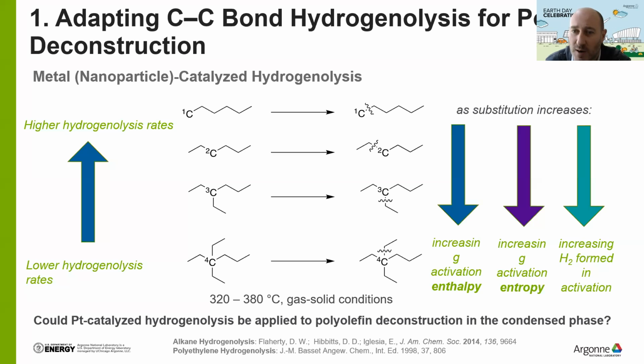The chemistry of carbon-carbon bond cleavage is well understood for small molecules. For example, there are metal nanoparticles that catalyze carbon-carbon bond hydrogenolysis, meaning using hydrogen to cleave carbon-carbon bonds. And this, as I mentioned before, is well understood in small molecules, C1 to C8. The translation from small molecules to macromolecules like polyethylene is not yet fully understood. And this is what we are looking at, for example, in iCOUP.